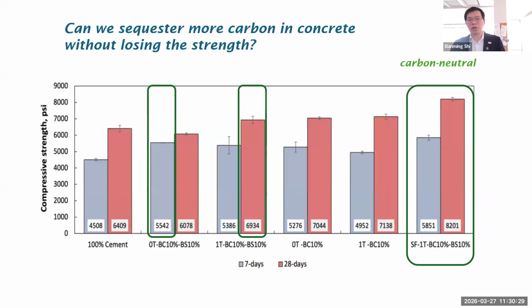Now the question becomes, can we sequester more carbon or CO2 in concrete without losing the strength? So we played a few different mix designs, as you can see here. I highlight the ones which are very promising. So roughly speaking, you can replace cement at 10% with this specific product. As I'll mention later, unfortunately or fortunately, I don't know, not all biochar products are the same. They are very different depending on the feedstock, the pyrolysis parameters. The devil is in the details.